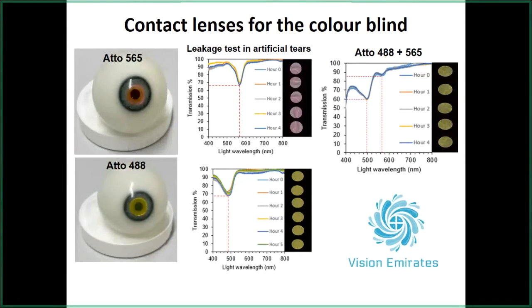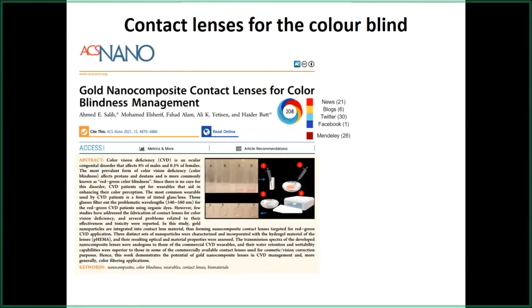Going ahead, for color blindness, the contact lenses we are making have to do just with filtering. Very recently, we used gold nanoparticles as well. Because of plasmonics, gold nanoparticles absorb almost the same colors. We used these gold nanoparticles mixed with hydrogels and made contact lenses out of them, and they also gave us the same sort of pinkish tint. We also compared their optical properties with the dyed contact lens and the ones which are available.